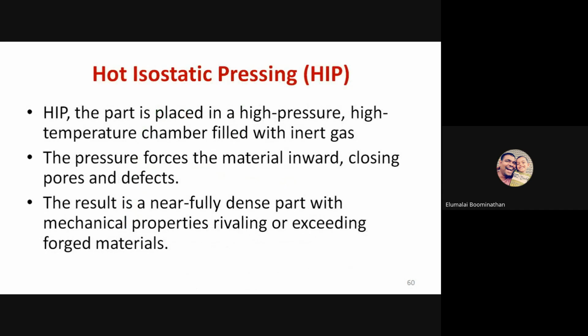And finally, we have the most important post-processing technology for SLS or any other powder bed fusion process. It is hot isostatic pressing, or HIP. In HIP, the part is placed in a high pressure, high temperature chamber, which is usually filled with inert gas. Isostatic means the same amount of static pressure is applied in all directions. This pressure forces the material inward, which closes the internal pores and defects. This usually results in a near fully dense part with mechanical properties close to, or sometimes exceeding, the forged components. HIP is widely used in aerospace and medical applications where the safety margins are very critical.